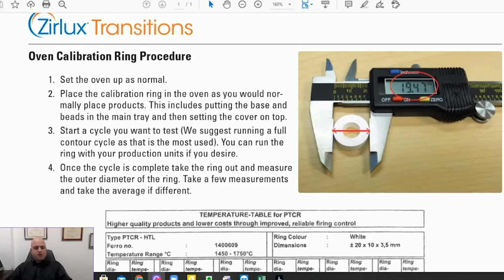By placing this ring into your sintering tray and sending it up with your restoration, once it sinters and comes down and cools, you can then take it over to a digital caliper, as you see here, and measure the diameter of this. This is a green state zirconia that is manufactured to have a very specific shrinkage that is dictated by the temperature to which it's subjected. It is a one-time use.